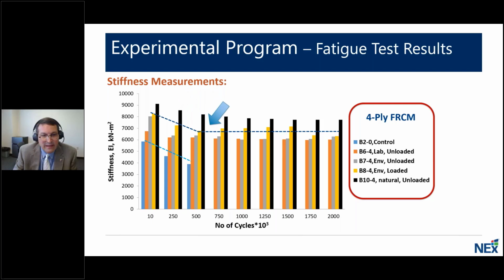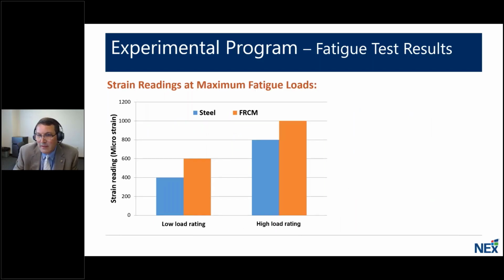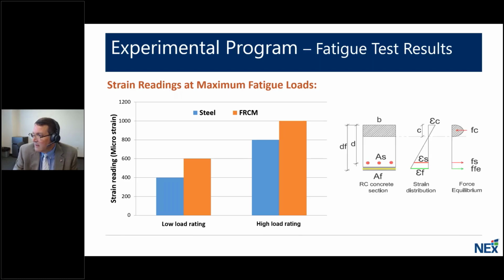And there again, you can see the degradation in stiffness early on during the fatigue testing, and the failure of the control specimen without any strengthening system. This figure shows the strain reading at the maximum fatigue loads, and clearly, if we take a look at the strain levels measured in both the steel internally and the FRCM externally, you can see that the FRCM system is carrying its load similar to what we would expect in the strain and stress distribution. So this confirms that the system is actively functioning and carrying the load.